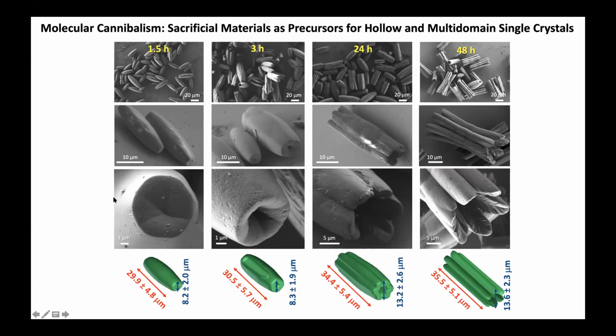You see at the edges some kind of structure. And in time, you see the crystals actually seem to dissolve. The crystals don't change much in the length, but the thickness actually is increasing. So we believe that it's a kind of inside-out Ostwald ripening process. You have here a kinetically formed system that is not very stable and starts to dissolve, and the material that is being dissolved is being added to the outside of these crystals.